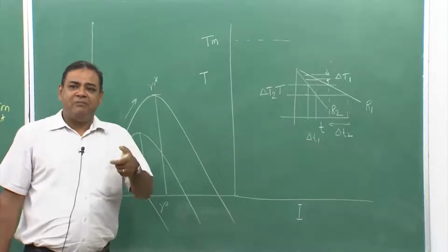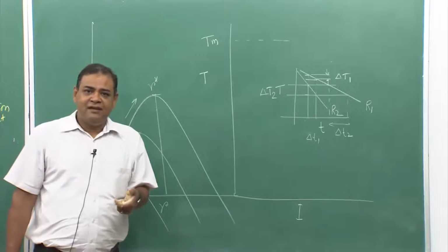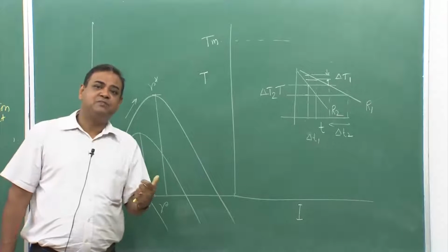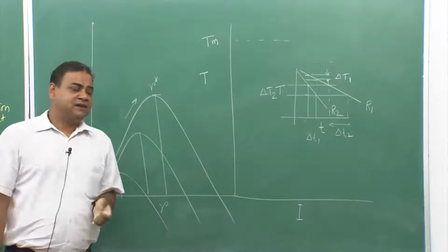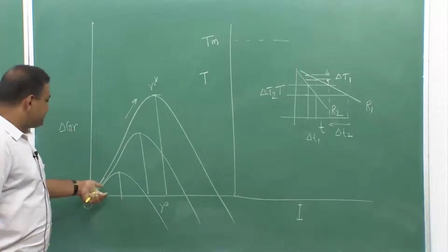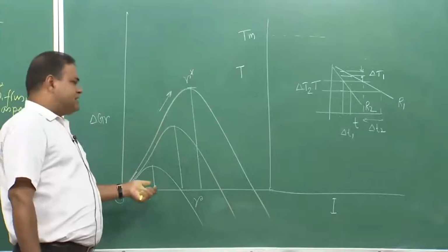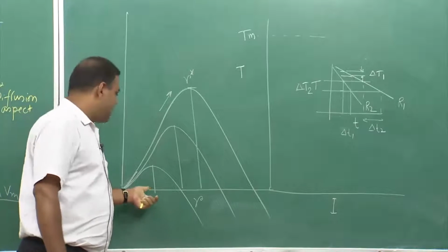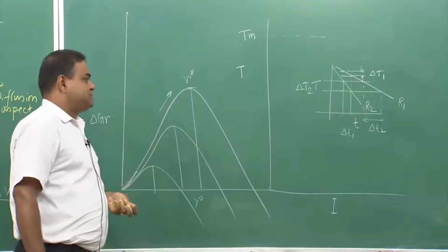That means I am reducing the critical radius because of higher undercooling, and that is because of higher cooling rate. So, this gives a little idea that yes, if we go for a higher cooling rate, higher undercooling, I would get finer structures.